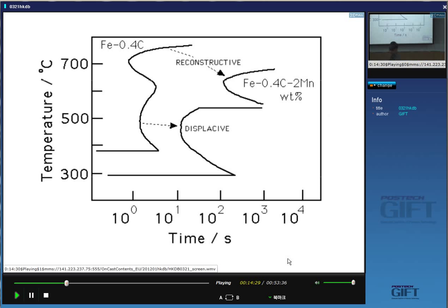That's why when you want to secondary harden a steel, because secondary hardening requires things like molybdenum carbide and so on to precipitate, that cannot happen at 400 degrees centigrade. You've got to temper your steel at about 500 or 600 degrees centigrade to get substitutional solutes to move.